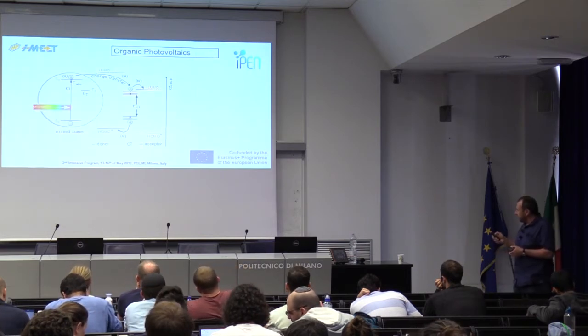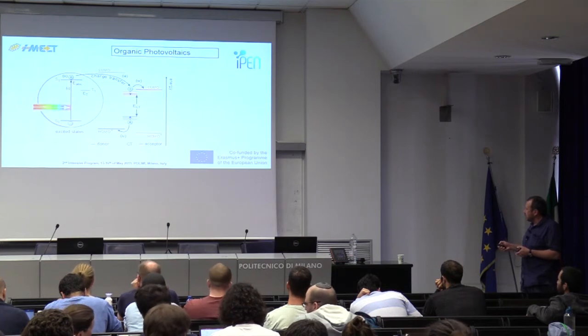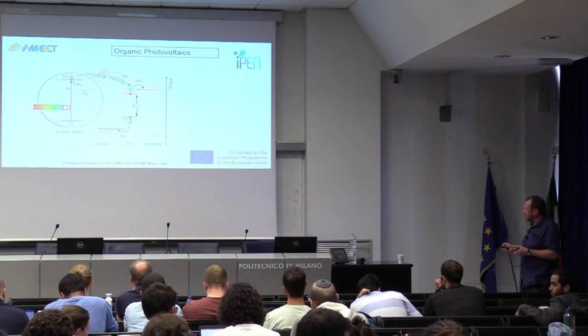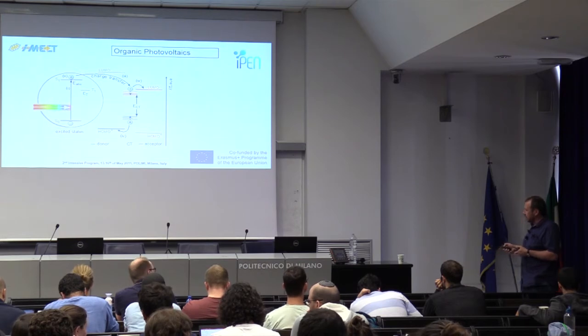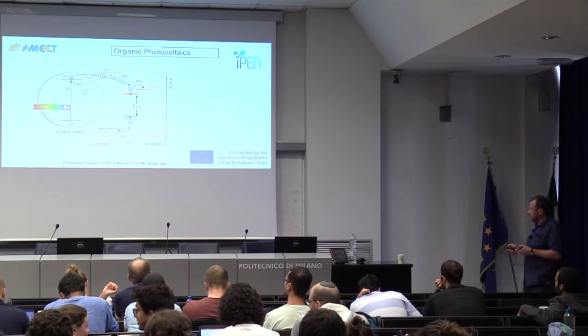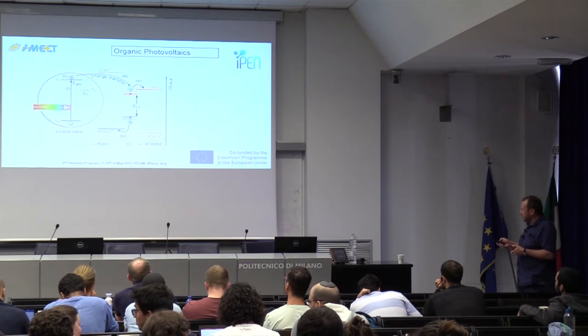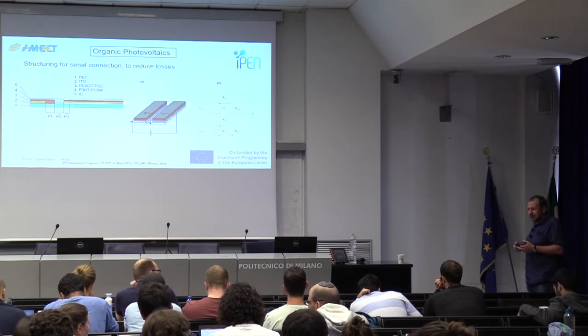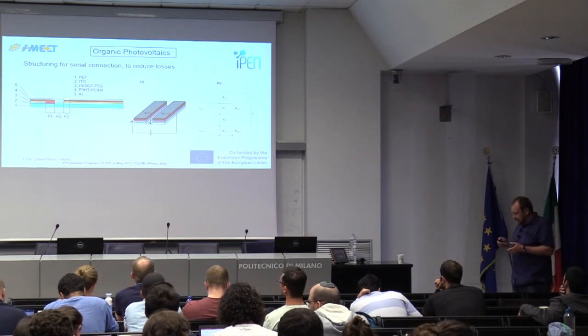The involved energy levels, shortly: it's not only about occupied and unoccupied levels, and the difference which should determine the open circuit voltage. Also several other energy levels are involved, like triplet states, and at the interface of donor acceptor you have also charge transfer states, and a lot of chemical engineering is being done to optimize these materials to increase the open circuit voltage.